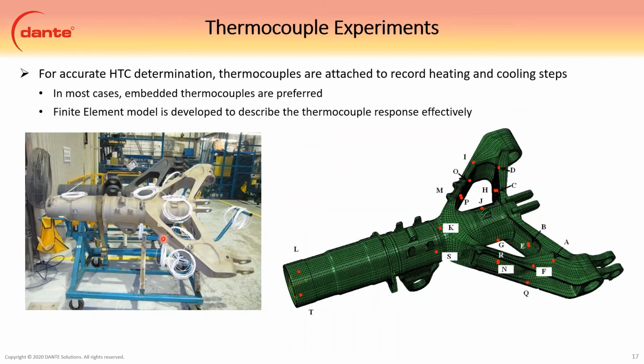So this was a large landing gear, with thermocouples welded on the surface. We actually prefer to get them embedded just a little bit, but this works. Then we build a model and fit the heat transfer coefficients from there.